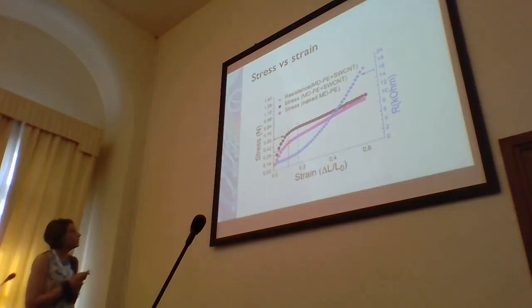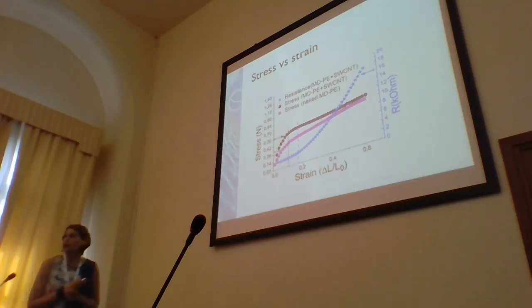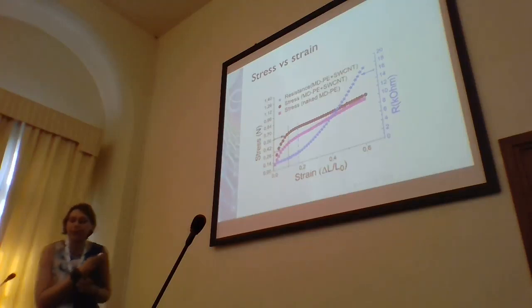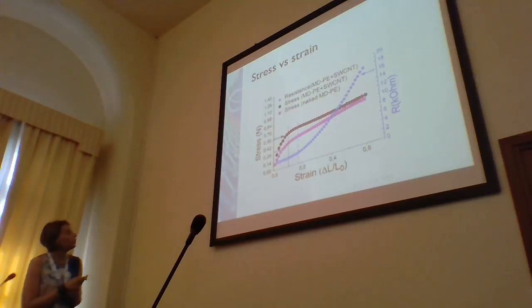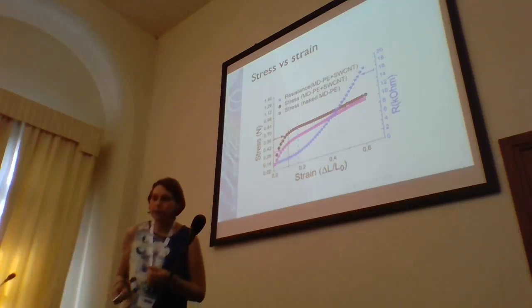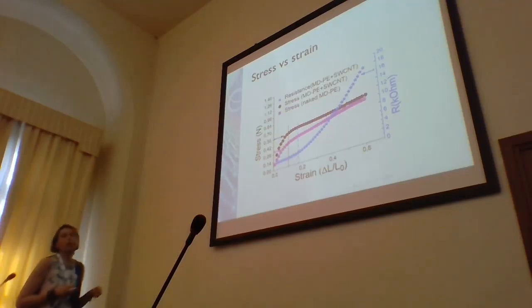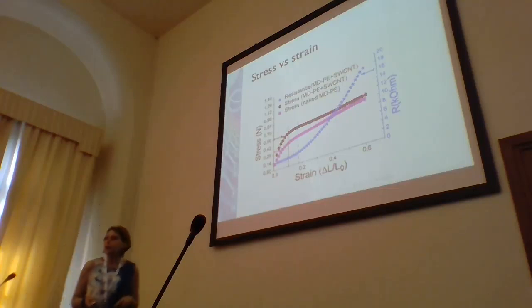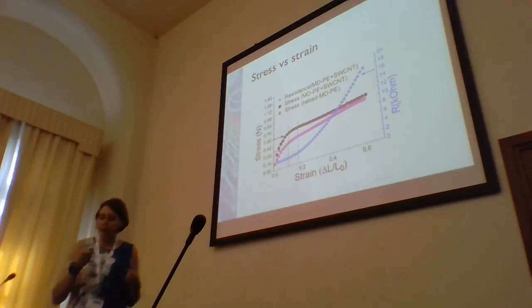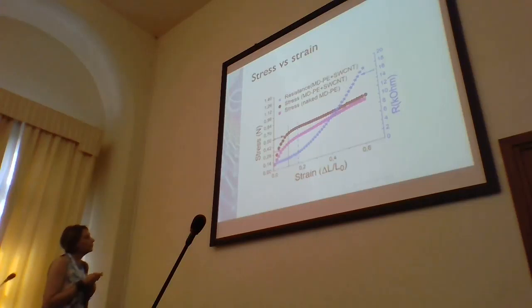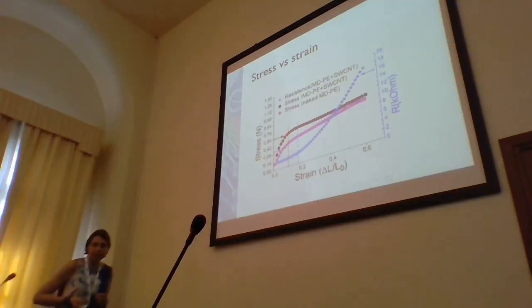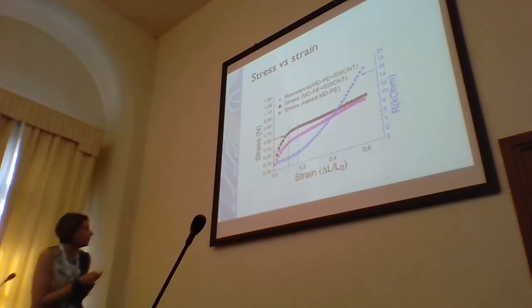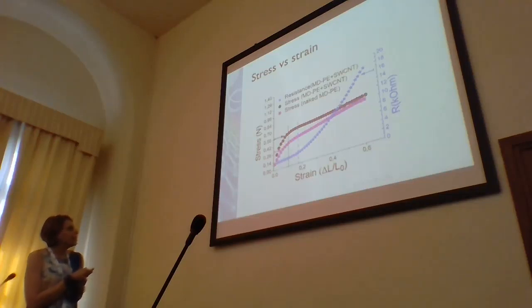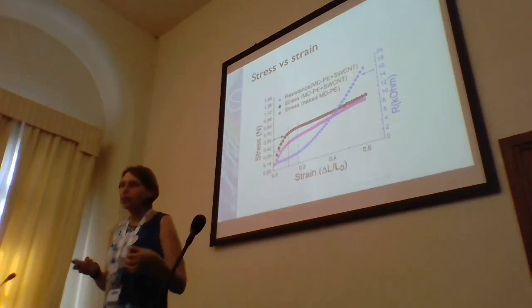This is a particular study of the viscoelastic properties of the naked medium density polyethylene, that you can see here in pink. The black is the composite material, and it is possible to see that when we put on single-wall carbon nanotubes, we give strength to the material. So we change this slope. This is in particular the elastic part, and this is the plastic part. But the important result is this: the resistance increases when the polymer is in the plastic part.